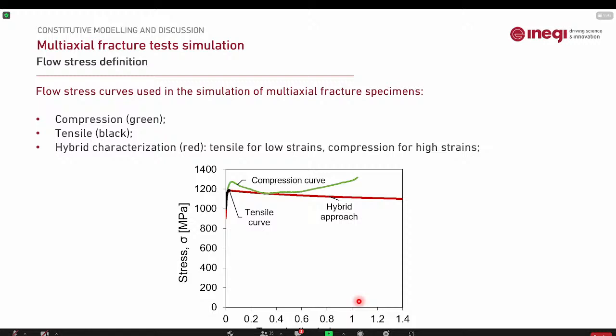Because if you have such a high strength material, you are even more sensitive to defects. Did you look at the fracture surfaces in the tensile samples? Yeah, we did, and we could find some porosity coalescence in the additively manufactured samples, which we attributed to their fragility, to their lack of ductility when compared to the conventionally manufactured.